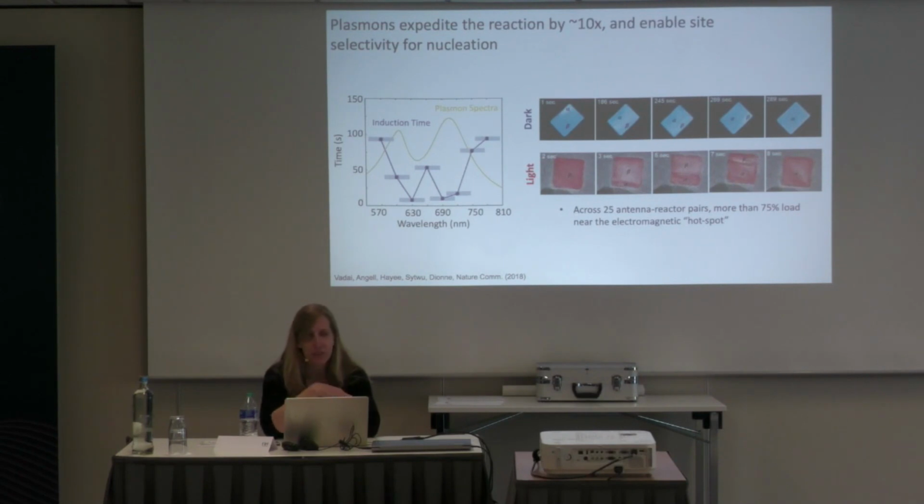And some of the experimental techniques that people have used would include SERS, like people have done Raman scattering, looking at the ratios of the Stokes to anti-Stokes peaks in Raman. Renee Frontera, I think she's at Minnesota, has done some really cool work basically extracting the temperature. So even though they're strongly absorbing, you're not causing significant heating, in part because of the particular mode. In this case, the mode is kind of centralized in the gap between the nanoparticles.